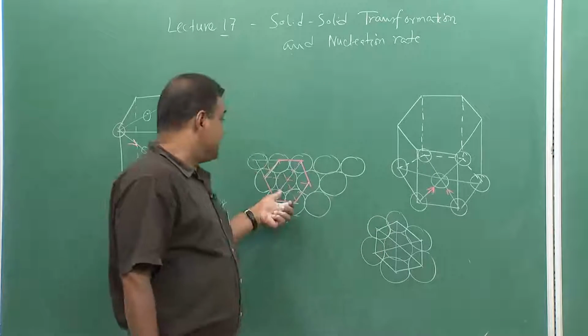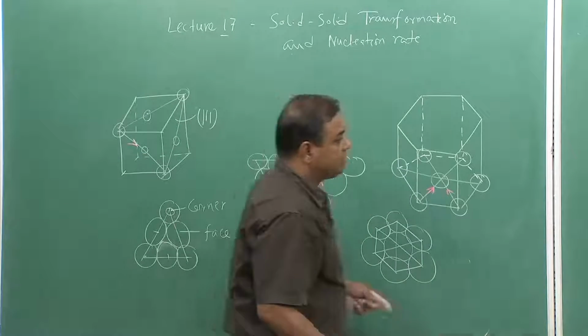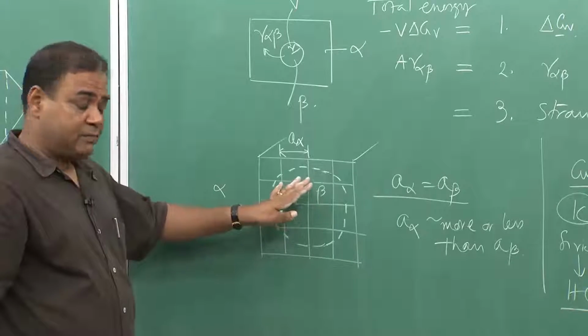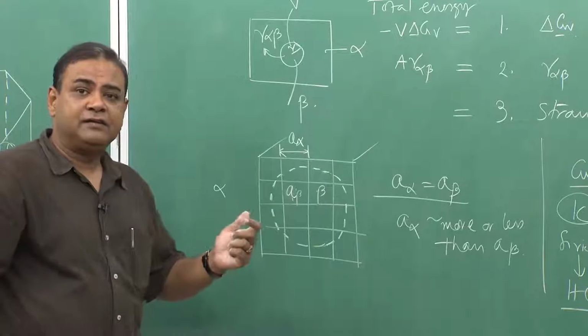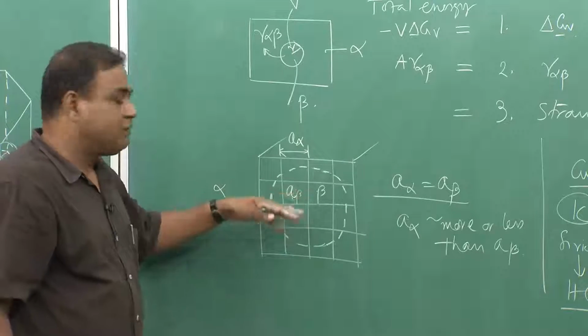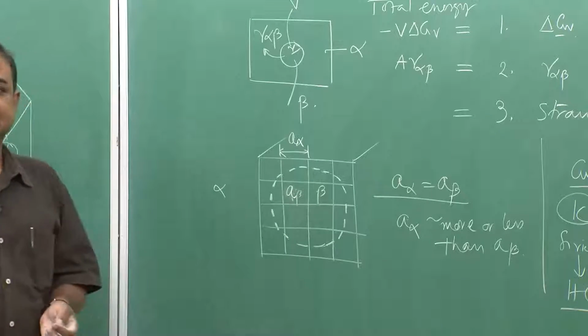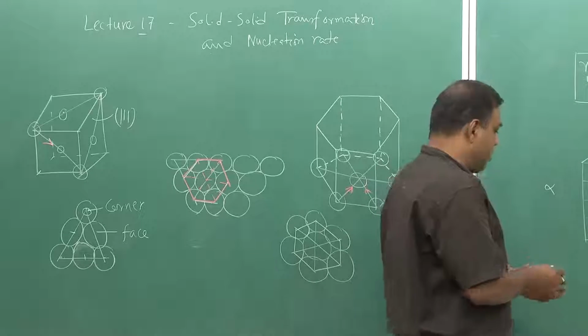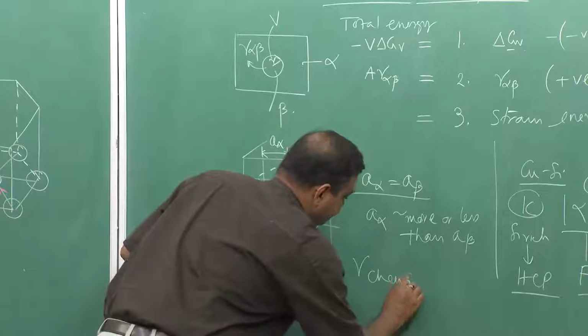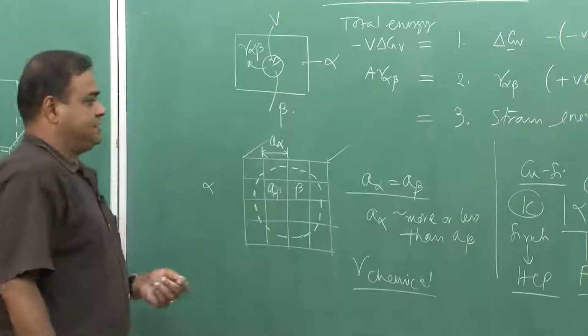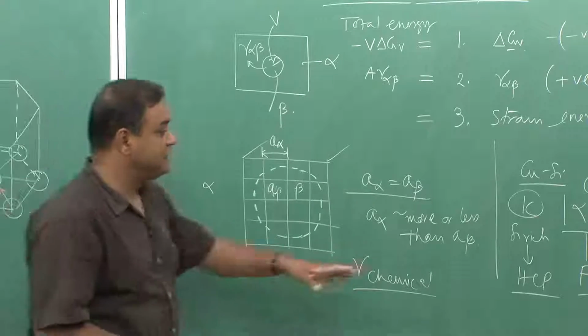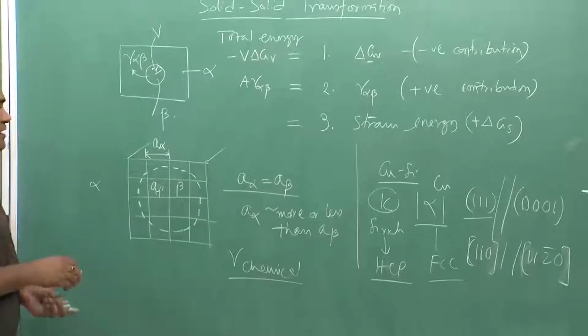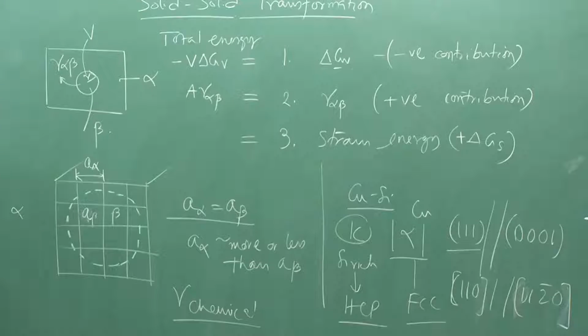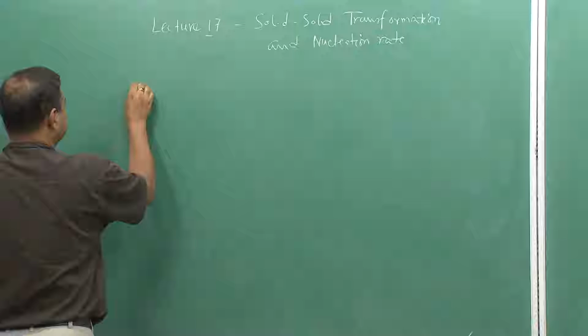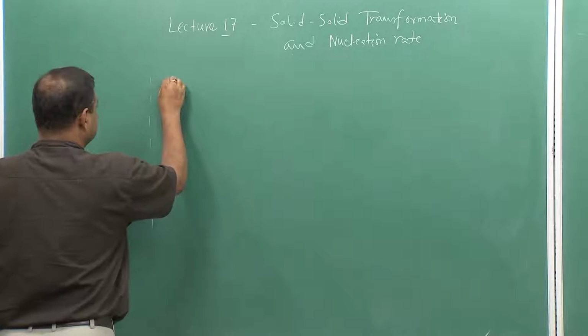But of course, if we have this kind of phase formation, alpha in a beta, beta in a alpha, we have an interface between alpha and beta. That interface energy is constituted by the chemical effect. So, we have gamma chemical. But the situation would be different if we do not find such a match. In that case we experience another kind of energy which is called structural interfacial energy. Let us look at that part. Now, let us draw it first.